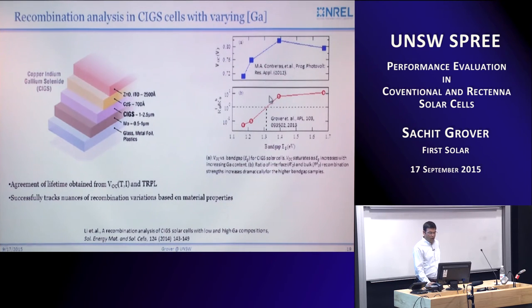When we did this analysis on their cells, and the data actually already existed, just had to plug it in, what we found out was that the ratio, so here is plotted the ratio of interface to bulk recombination. We found out that for the low band gap devices, the bulk was the dominant recombination, but as we increased the gallium concentration, the interface recombination started to dominate. So that's kind of in line with the Fermi pinning theory, but here's direct evidence, the fact that interface recombination is limiting the VOC for those band gap values. And that was published in 2014 in this paper.